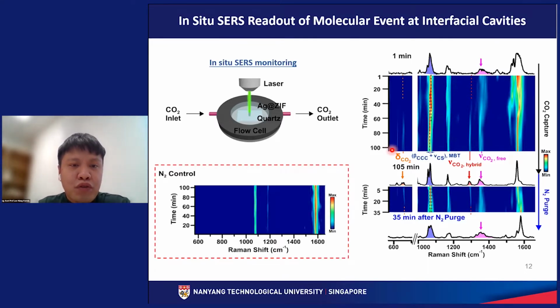Okay, so next we try to flow our gas flow cell using nitrogen for the entire 105 minutes. So in short, there is no carbon dioxide, there is only nitrogen. So from this time-dependent SERS spectrum, we can see that there is no change to the SERS feature of our methyl benzene thiol probe.